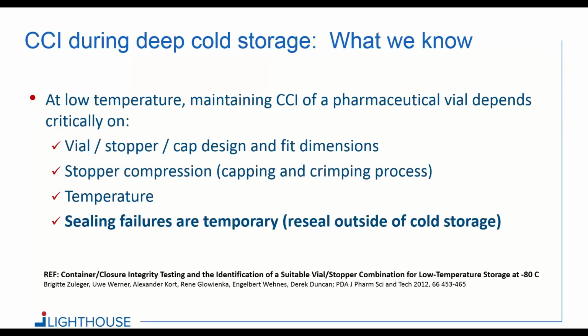What's been interesting is these studies have shown that the sealing failures caused by deep cold storage are actually temporary. You can have a vial that has good CCI at room temperature, put it into deep cold storage, and it loses its closure at the deep cold storage temperatures. When you take it back out of storage, the vial warms up and it will actually reseal. The consequence is that it's more complicated to detect. You'll see down at the bottom of your screen a reference. This was a publication back in 2012 in the PDA journal, which goes through a lot of these things in more detail if you're interested in looking that up.